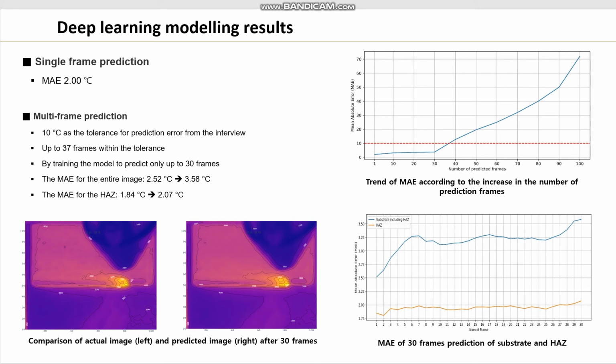This figure shows the mean absolute error trends for the entire coating layer and the heat affected zone within 30 frames. The mean absolute error trend for the entire coating layer differs from that of the heat affected zone. As the number of time steps increased, the mean absolute error for the entire coating layer increased from 2.52 Celsius degrees to 3.58 Celsius degrees. But the mean absolute error for the heat affected zone increased by only about 0.2 Celsius. These evaluation results show that the performance of the proposed model is very good.